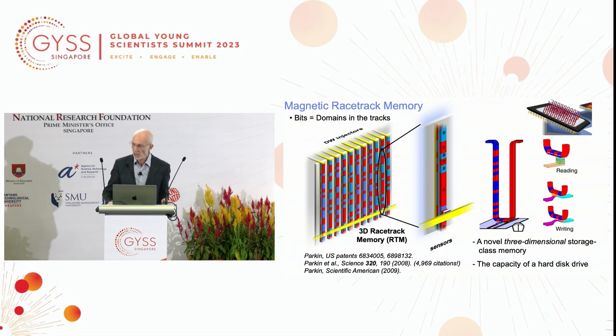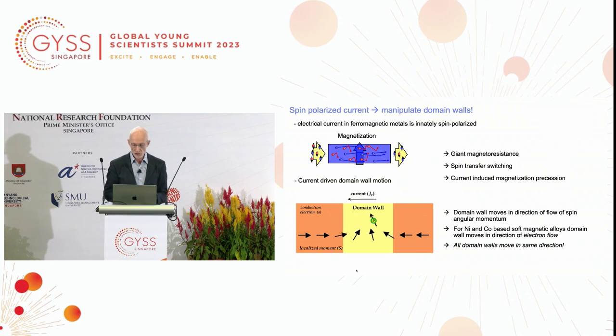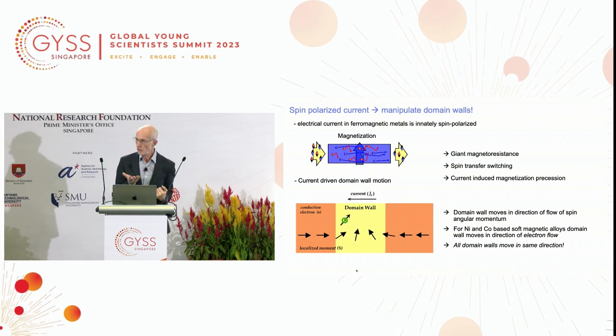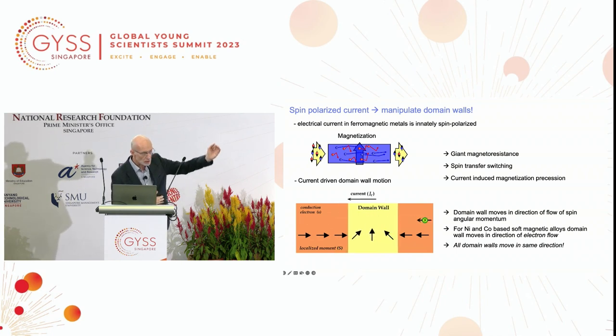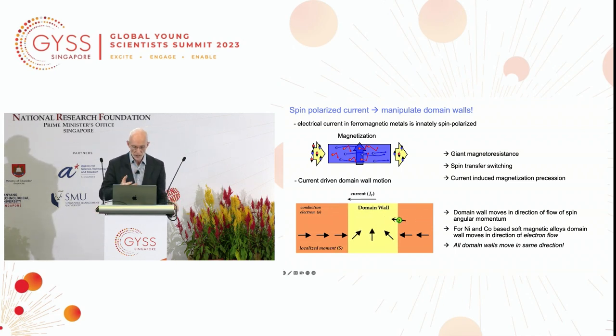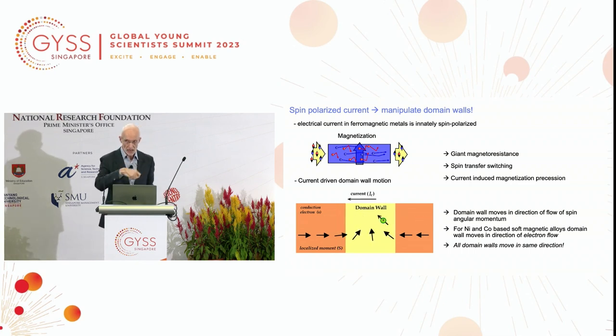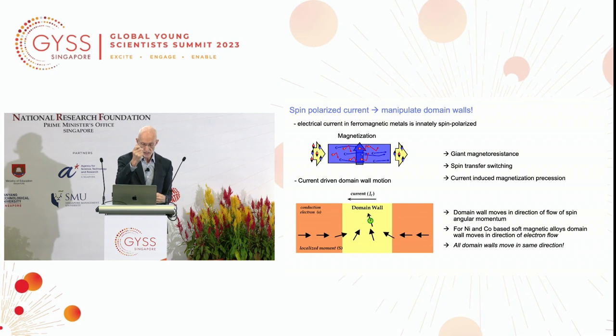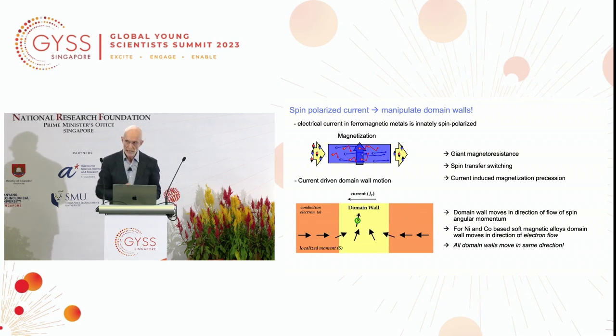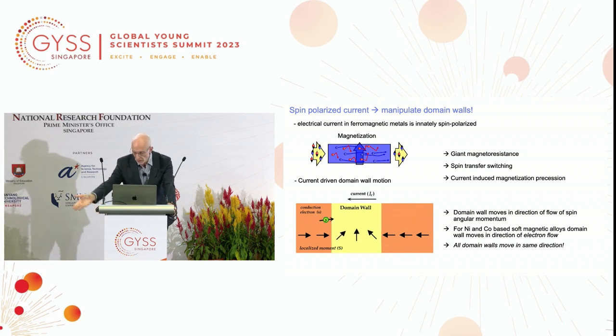But again, we had to go beyond that and discover much new physics to make it relevant technologically. How does this work? As I mentioned before, you take a current in a magnetic material, it's spin polarized. And that spin angular momentum of these conduction electrons, shown as these moving electrons in this cartoon, we can transfer that spin angular momentum to the magnetic moments in the domain wall. Roughly speaking, every time we introduce a polarized spin, it can rotate a single magnetic moment. So we need to pass enough current through this material to move the domain walls. And that's something, I said, we demonstrated for the first time in 2008.